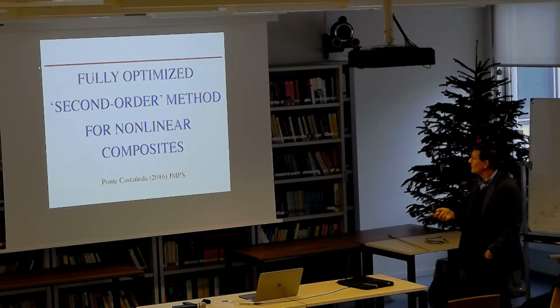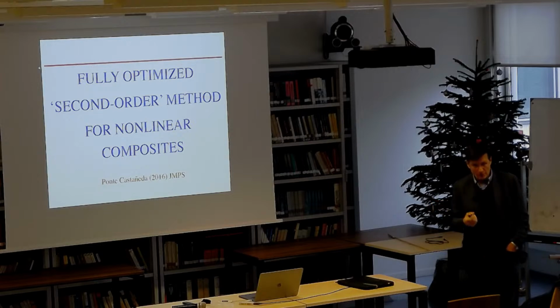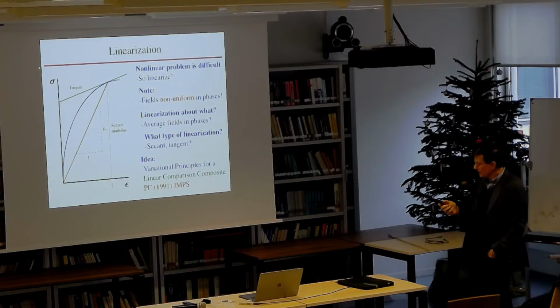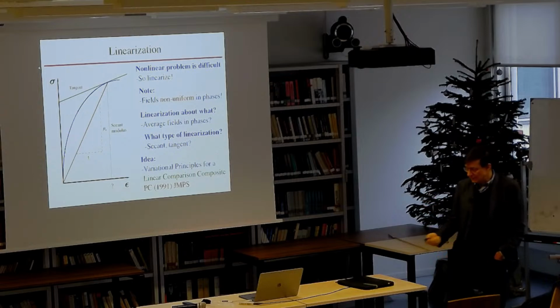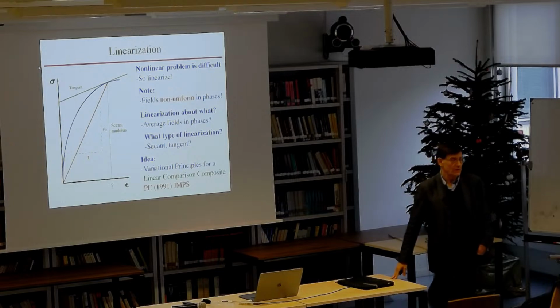this fully optimized second order method, which is concerned with how we deal with the nonlinearity in the phases. I'm talking about the nonlinearity in the constitutive response. So if this is the stress as a function of the strain, the constitutive relation may be something like this blue line here. It's nonlinear. And unfortunately, the methods that have been used very effectively to get information on the microscopic response of composite materials or heterogeneous materials with linear constitutive behavior don't work for nonlinear materials.